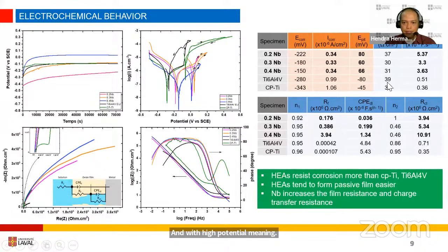Okay, and from electrochemical impedance spectroscopy, we can obtain some resistance, because after we obtained this curve, which we call a Nyquist curve, we did some fitting with this proposed electrical circuit model. From this, we can obtain some electrical parameters, like resistance of the solution and resistance of the film. There is also some capacitance, or a mix of capacitance and resistance represented by this CPE, constant phase element. And also we have the resistance of charge transfer.